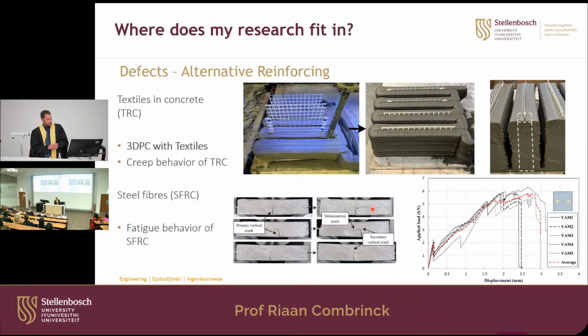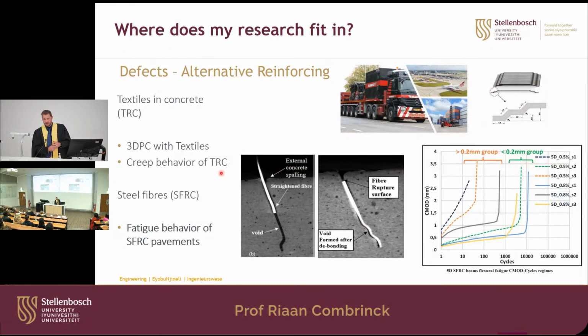Okay. Then alternative reinforcing, we've been looking at using textiles in concrete, especially 3D printing concrete as well, and then testing it and seeing how the cracks developed. And you'll see this is the load versus displacement graph. Just normal concrete just goes up and cracks, but once you add the textile reinforced concrete, you can see there's a much more tensile capacity that you can get from your concrete. We're also looking into creep of textile reinforced concrete, and then also using of steel fibers in concrete.